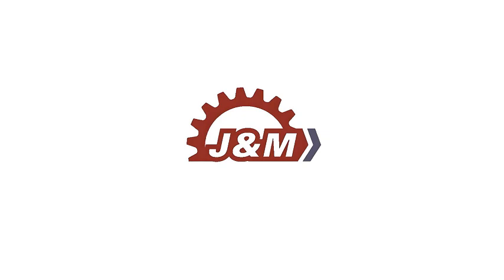Is there a trade-off? Oh, the precision is definitely impressive. We can reliably achieve dimensional accuracy down to plus or minus 0.002 millimeters. That's 2 microns. 2 microns. Okay. And the surface finish can get smoother than Ra 0.4 micrometers. Ra is roughness average. It's how we measure texture. And 0.4 is exceptionally smooth. It's almost mirror-like, but it has this non-directional matte texture, which is actually great for holding lubricant on a working die surface. Oh. So yeah, we're operating at the micron level.